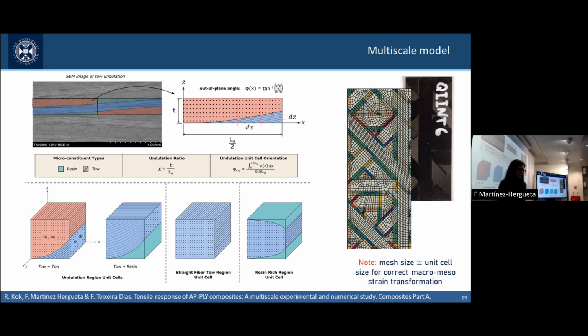These undulating regions can be represented with 4 congruent sections that contain either 2 tows or a tow and a resin rich region. Some of those tows in these unit cells are undulated. We have introduced the undulation following the equation over there as an average, and they work as unit cells. So we consider the volume of each material in each unit cell, and we do the volume integral in order to homogenize the response.